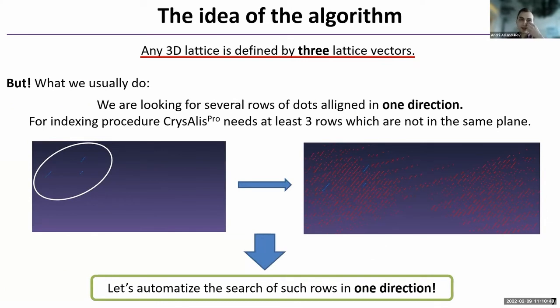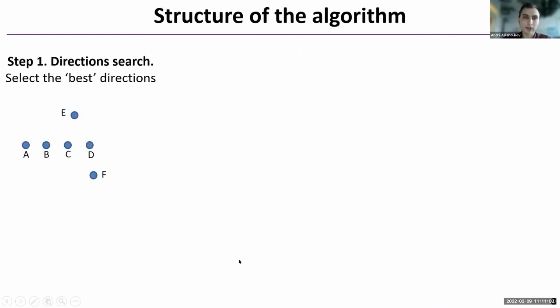So the general idea. Of course, any 3D lattice is defined by 3 lattice vectors. But as I showed you before, usually we are looking for several rows of dots lined up only in one direction. And this is enough for Chrysalis. So that's why the idea of the algorithm is very simple. Let's just try to optimize the search of such rows in one direction. So the first stage of the algorithm is to select the best direction. It can be done by brute force search through all pairs of points.